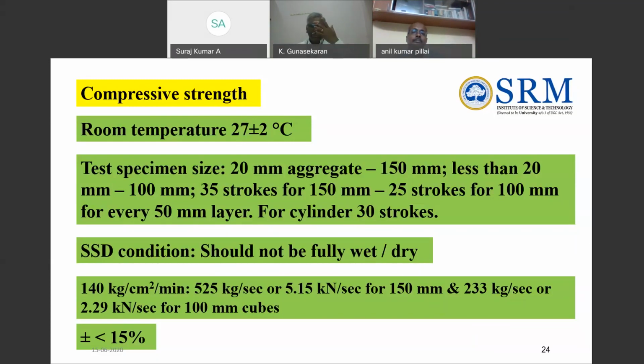Nowadays it is digitally available in your CTM and UTM. But whether you are applying the rate of loading correctly or not, if you switch on the equipment, it will automatically show the readings. But in what way it is adjusted, nobody is taking care of that. So you must take care of the rate of loading, because that will also affect the strength of the concrete. If you are using a 150 mm cube, see that the rate of loading per second is 525 kg or 5.15 kilonewton. It is based on the calculation of surface area only. If you convert this 140 kg per centimeter square per minute in terms of your cube size as well as per second, this value will come. Similarly, if you are using a 100 mm cube, the rate of loading per second is 233 kg or 2.29 kilonewton per second.